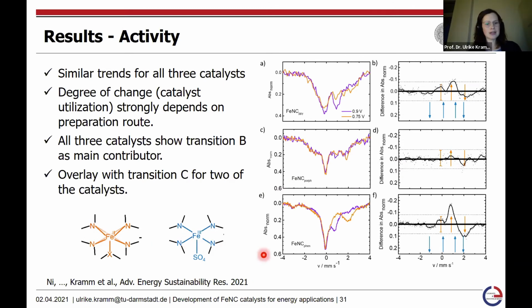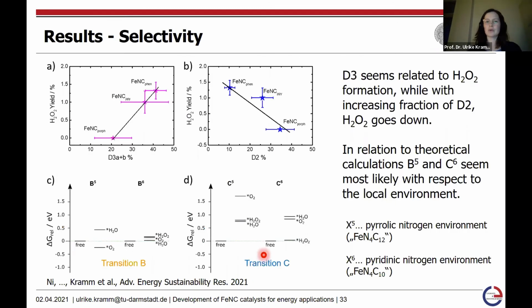When we investigated this a little bit further in combination with DFT calculations, we can assume that for one of the catalytic sites, we have pyrrolic type coordination of the iron by 4 nitrogen atoms, and if we have an additional axial ligand, this site is responsible for the direct reduction of oxygen, but also to a small quantity for the hydrogen peroxide formation.